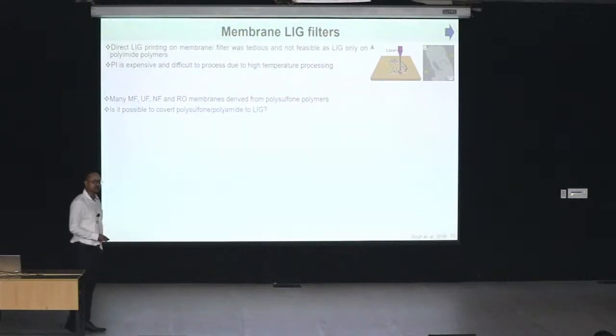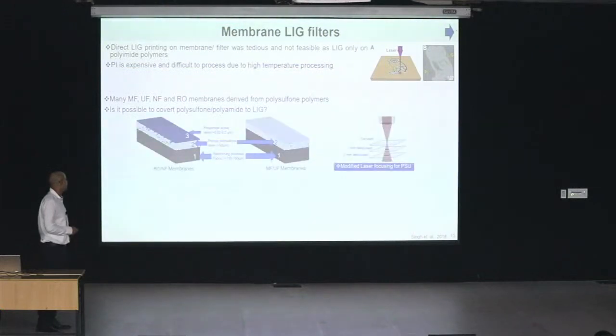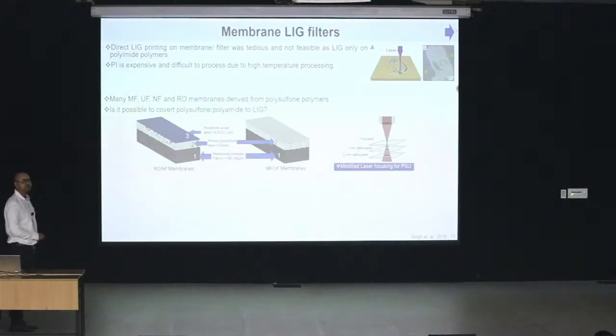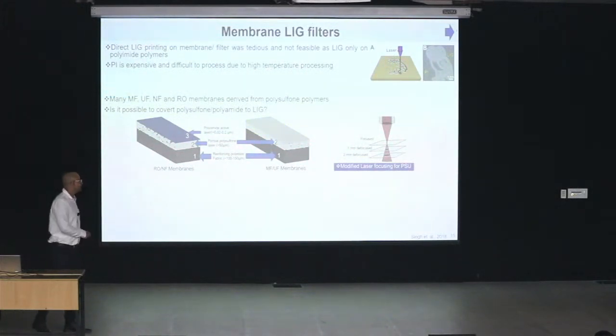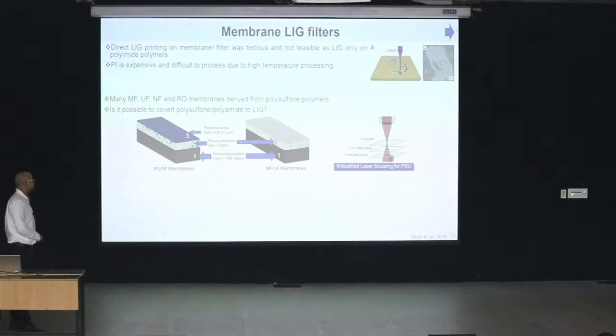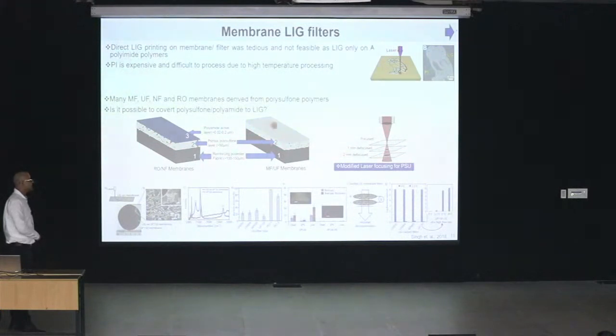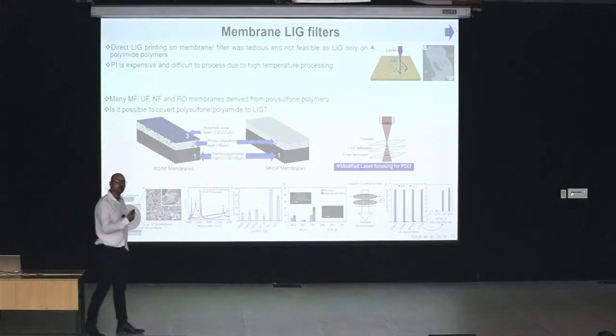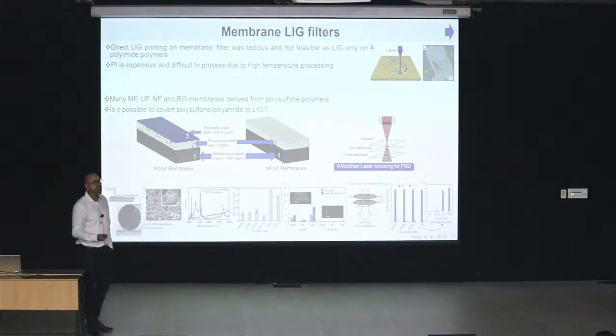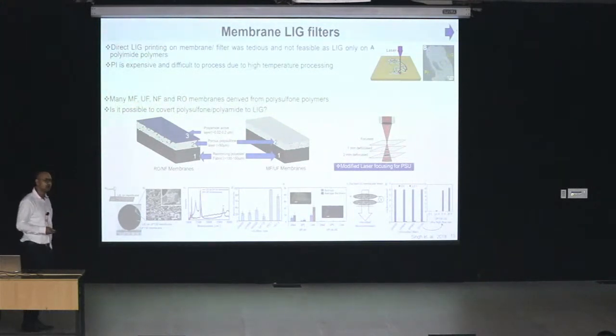We are making different kinds of ultrafiltration membranes, microfiltration membranes, and also they are the basis we use as a support layer for nanofiltration and RO membranes. So later when we tried to investigate how this laser is converting polymer to graphene, we found out that with a proper laser setting, we can go for defocusing or multiple lensing, and we can convert any kind of carbonaceous surface into graphene. Obviously, the qualities may differ. For example, polyimide in a single-step laser burning gives very good quality laser-induced graphene, whereas certain materials like PVDF you have to do multiple lensing, but still the quality is not matchable with polyimide. But what we have seen is that the polysulfone class has many different polymers, but one of them, polyether sulfone, is very good, very nicely converting into laser-induced graphene.